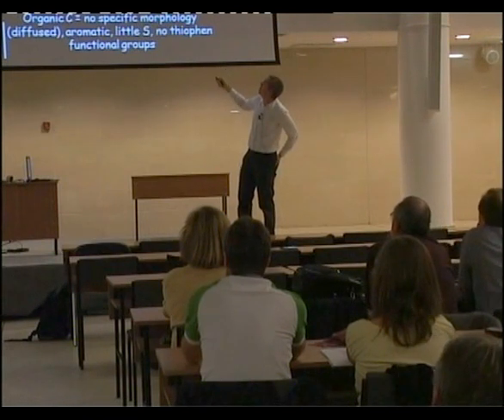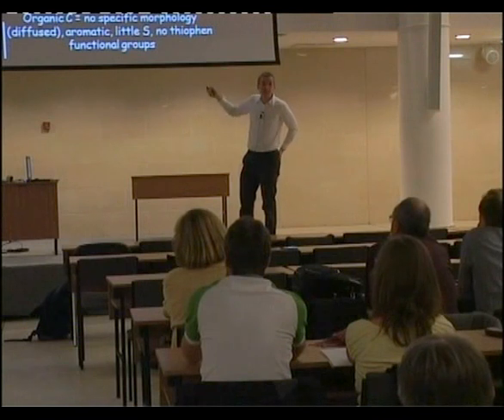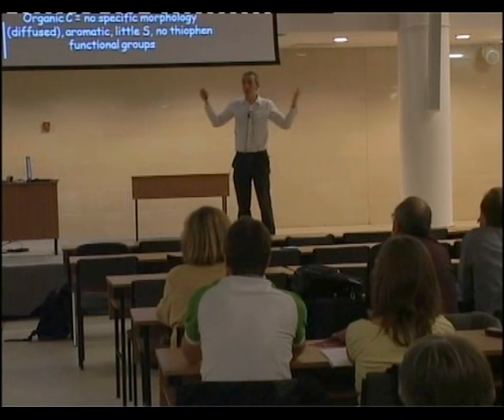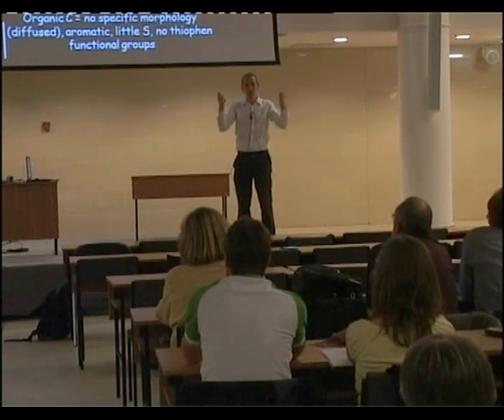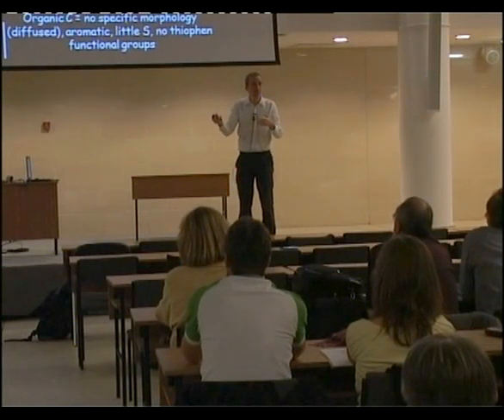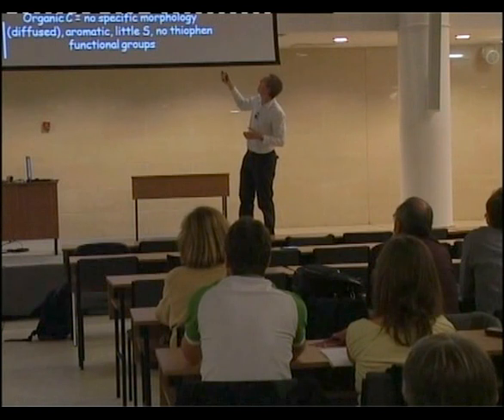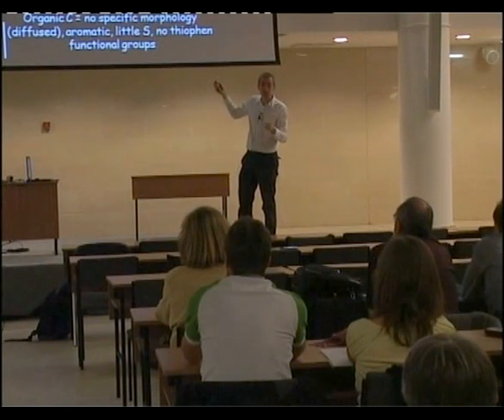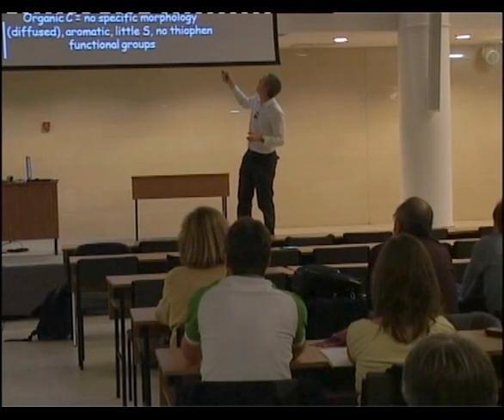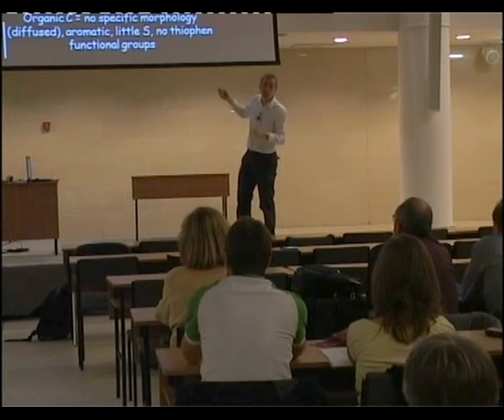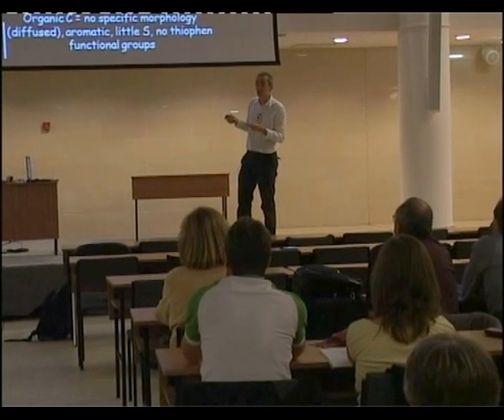Here, at the time you formed the chlorite, there was a lot of iron too in the solution. So the iron too trapped the sulfides, and there was no sulfur left for the organics. So the organics did not get sulfurized, and the organics then, the morphology was completely destroyed and changed.